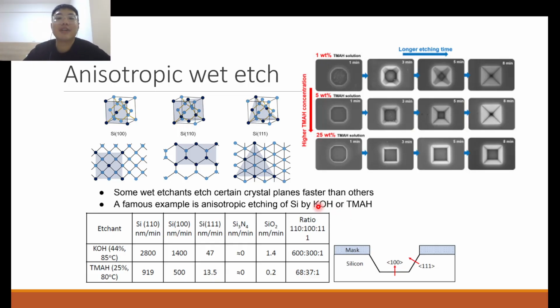And what's the reason for that? Actually very simple. You look at 100, look at 110, look at 111. Which plane will have the fastest etching rate, and which one will have the slowest etching rate? The answer is that the slowest etching rate is your 111.